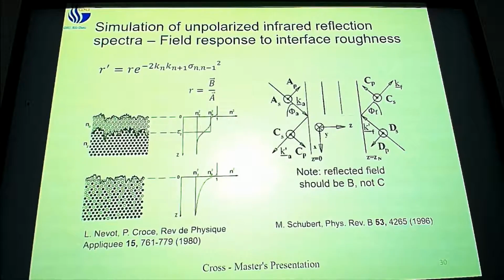If you didn't see any roughness terms up until this point, Nevot and Croce defined a model back in the 80s, but you can see it's defined for this model here where this is the ratio of B and A. Again, not C, B. This works very well when I have these terms exactly, but now I need to incorporate that into a 4x4 matrix method where there may be differences in the directional components of my dielectric function as well, which affects these K vector values. So that's what I'm going to be working on as well.